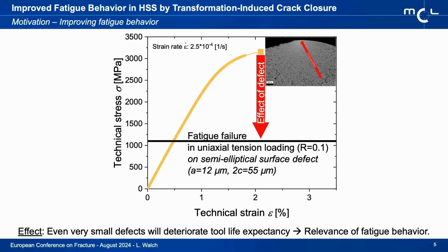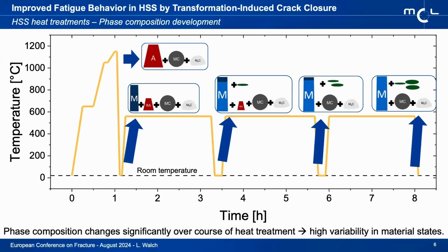Still, it raises the question, what's the point of having all this mechanical strength if it can't be used at all? Which leads us to a fatigue-centered approach in furthering the high-speed steels themselves, which is very difficult if you try to do it with changes in the chemical composition, because just a small change in the chemical composition can significantly alter the outcome of the final product without you having any real option of finding out beforehand. That's highly time-consuming and very ineffective.